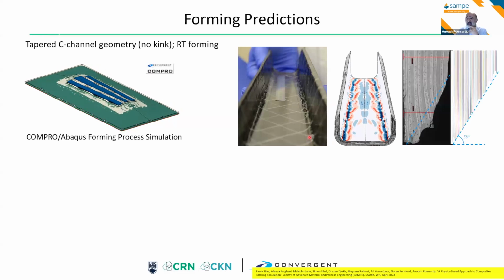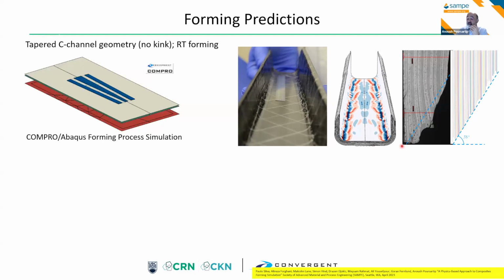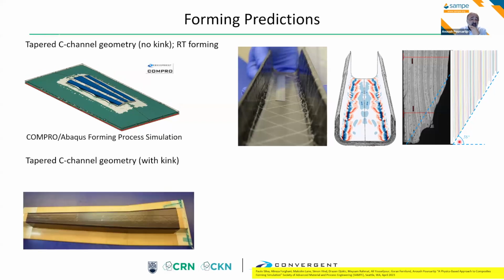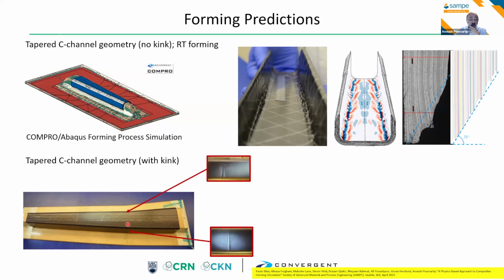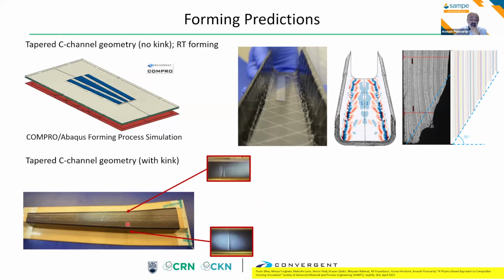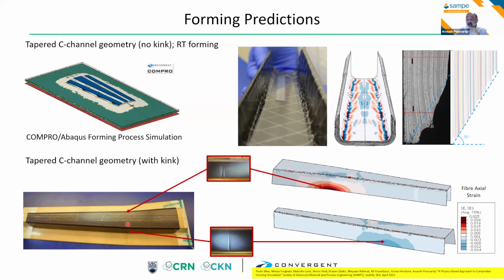And you can also look at things such as the edge of the end of the flange, and you can see that you're seeing a lot of shearing between the plies, which is actually very desirable. And again, the models pick it up. If we look at, say, a tapered geometry with a kink in the geometry, we will typically get wrinkles, both the inside and the outside of that. And again, if you look at your fiber axial strains, the models will show that.